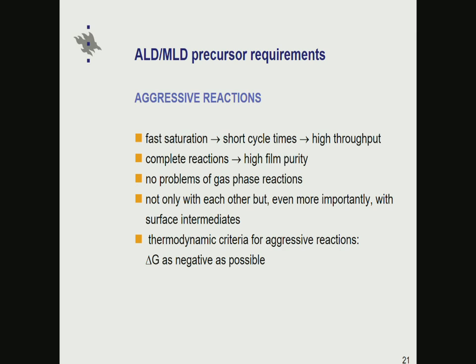Okay, then the next requirement is to have aggressive reactions. The reason we need aggressive reactions is that ALD is slow. How can we make it faster? By saturating the surfaces in as short a time as possible, and by choosing precursors which react aggressively with the surface intermediates left by the other precursor, one can shorten the cycle times, and in that way also increase the throughput. Aggressive reactions usually also mean that the reactions are complete, which leads to high film purity. We don't need to worry about gas phase reactions, as already said, because these precursors are not in the gas phase at the same time.